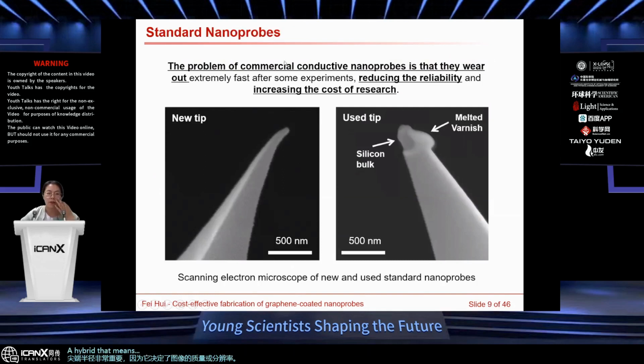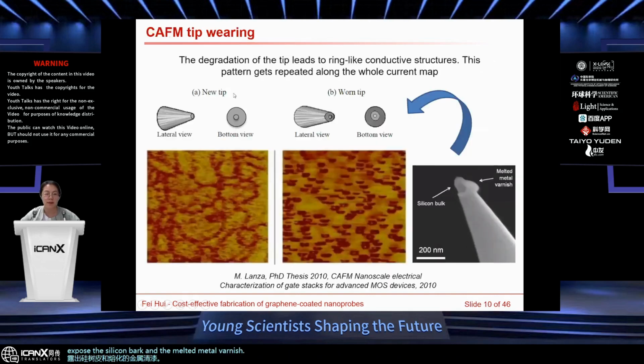However, the main problem of commercial conducting nanoprobes is that they wear out very fast after some experiments, especially when they bear high contact force or high current densities, which will reduce the reliability and increase the cost of research. And here, I show two SEM images. The left image shows one new tip, and the right shows one used tip. And we can see from these images that the exposed silicon bulk and the melted metal varnish after some scans. As a result, the degradation of the tip will lose its conductivity, or in this case, it leads to repeated ring-like conductive structures.